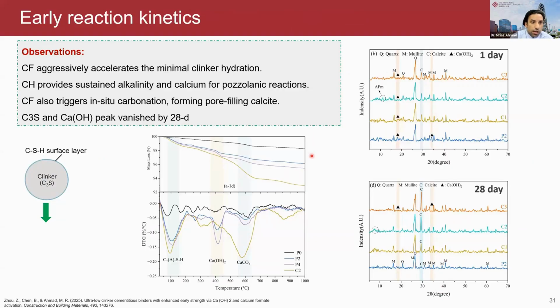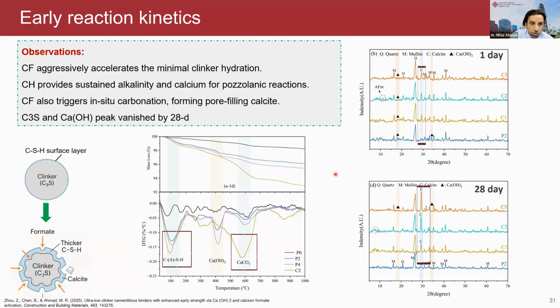So why does it happen and how does it happen? We further tried to study what the different mechanisms are. So we propose 3 different mechanisms which happen in this kind of system. The first one is that the calcium formate aggressively attacks the clinker and increases its hydration at a very, very early age. The second one is a substantial increase in the volume of the CSH gel,